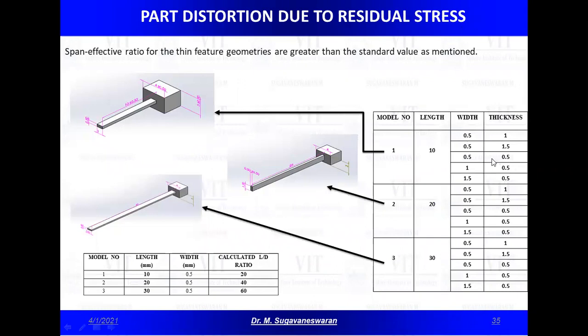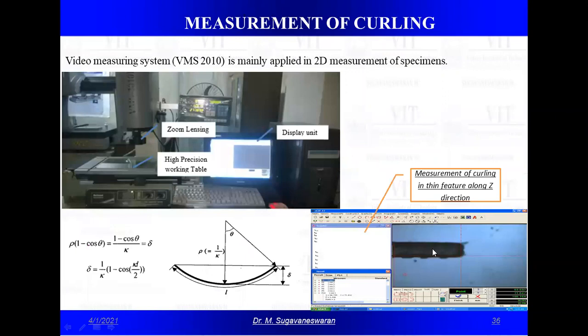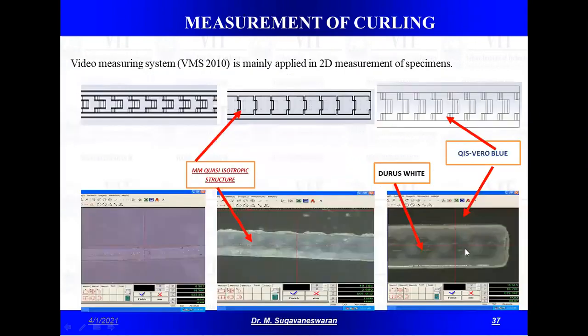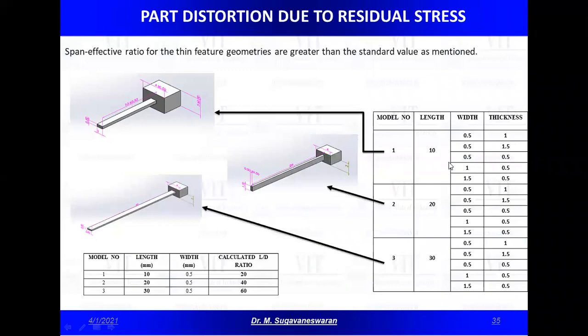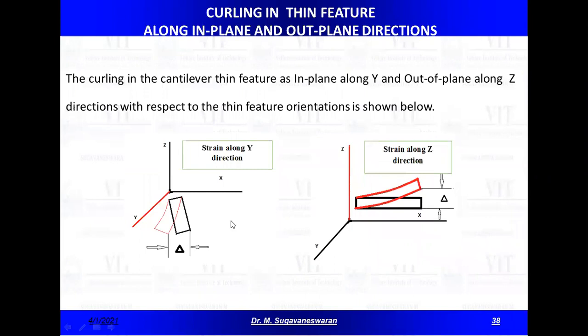designed different L by D ratios with different thicknesses, and the same thin strip is manufactured through a single material condition as well as a multiple material condition. After removal of the part from the component, the curl distortion in the thin feature is measured. So this is a printed component of a thin feature based on the quasi-isotropic condition. In the enlarged image, we are able to see the multi-material condition. The dimensional combinations we have taken are shown here: different widths, lengths, and thicknesses for the purpose of experimentation. We are able to observe in-plane distortion as well as out-of-plane distortion.